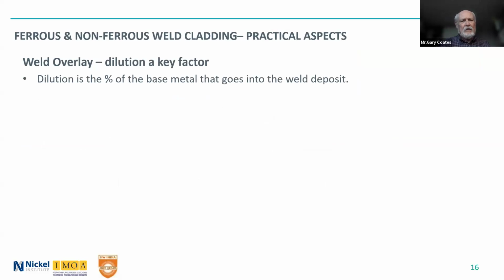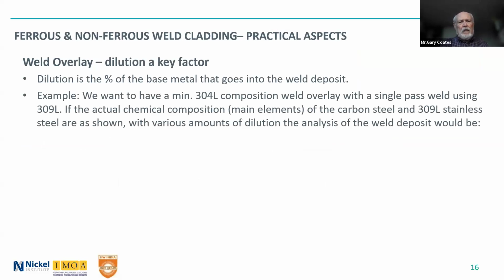So dilution, as a definition, is the percentage of the base metal that goes into the weld deposit when we're talking about a weld overlay. So, for example, I'm going to take a case where the end user wants a minimum of a 304L stainless steel composition on the weld overlay, and you want to do it with a single pass weld. Most often you don't, but we're taking that here using 309L, which is the filler metal that you normally would use if you're welding stainless to carbon steel.